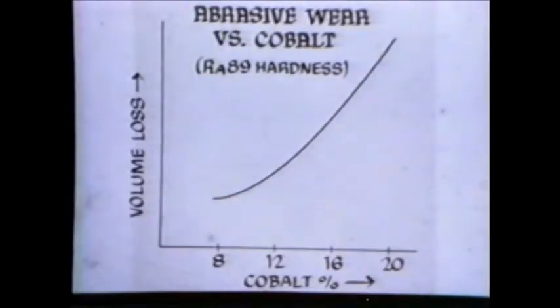Abrasive wear is also a factor. Here we see the relationship between abrasive wear and cobalt. The abrasive wear is basically the bar wearing the carbide as it passes through the die. The higher the cobalt content, the greater the wear and the lower the die life. Other factors such as grain size affect the carbide, but nothing affects the physical properties as drastically as the cobalt content.